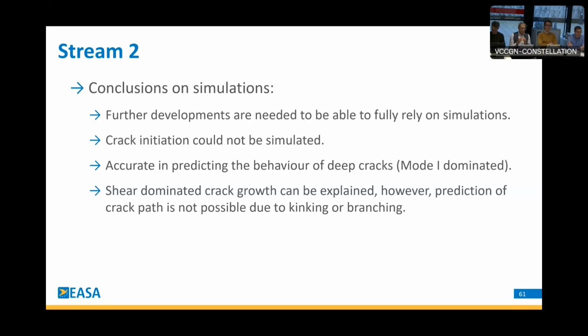The simulations seem to work quite well to predict what could happen, so predict that the crack could kink or that it could branch into several cracks, but at the moment the tools that were used for this research project, at least, were not capable of making that differentiation of when would it happen, when would it not, and how to determine how the crack will actually behave in detail in these conditions. However, for detecting that when this was possible, it worked quite well.